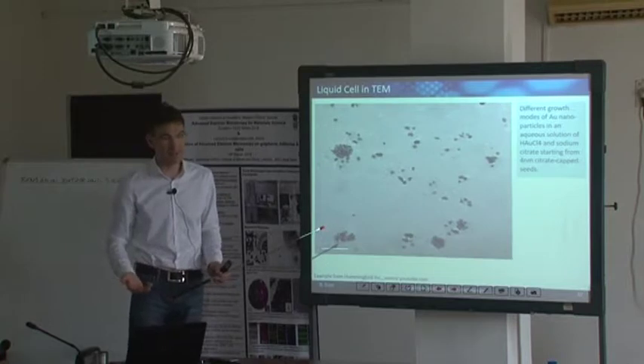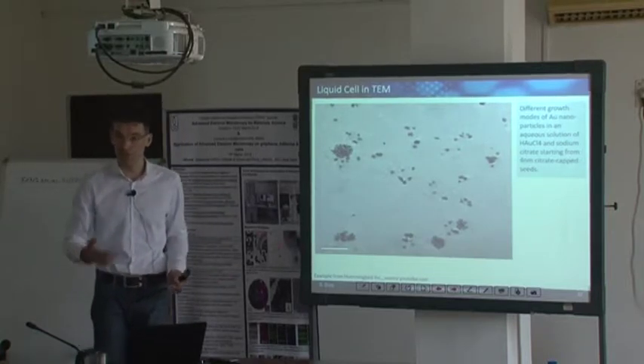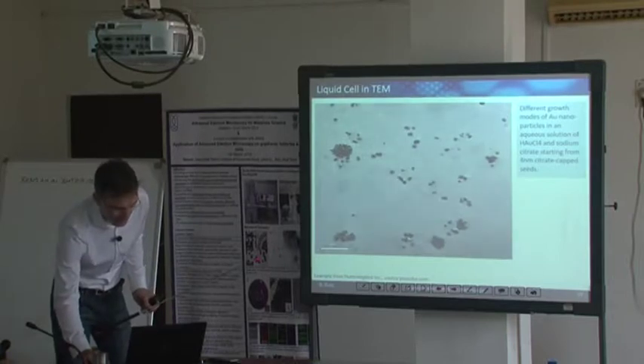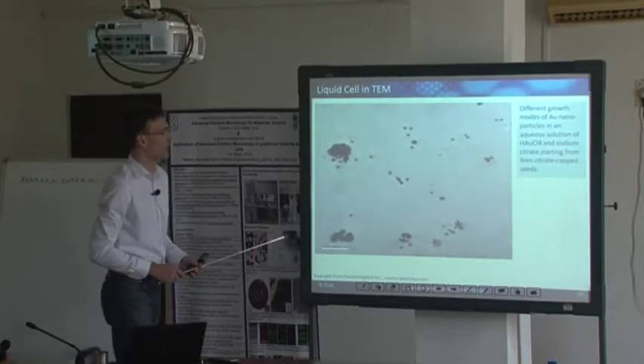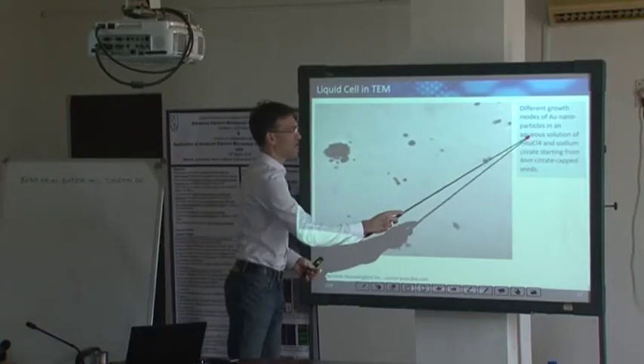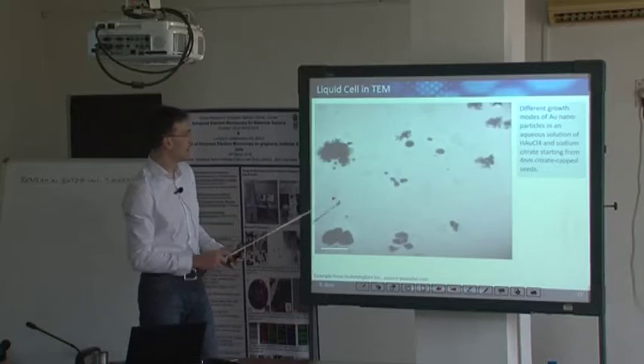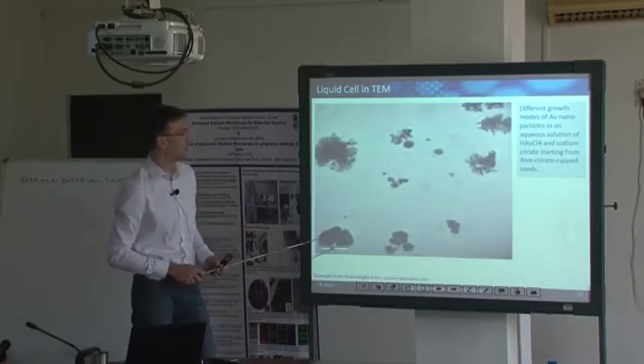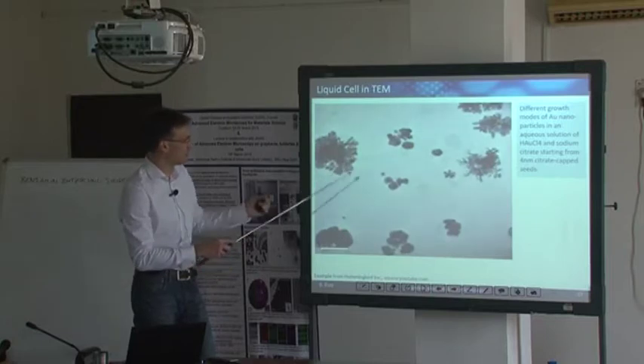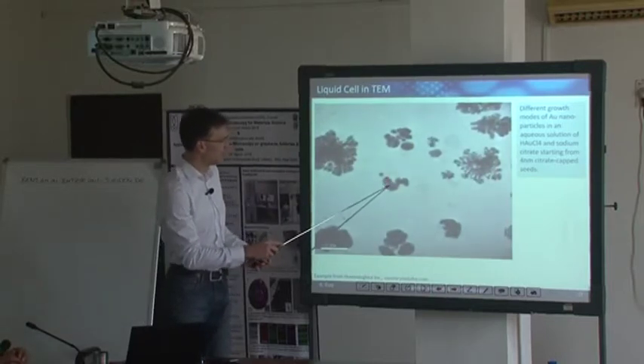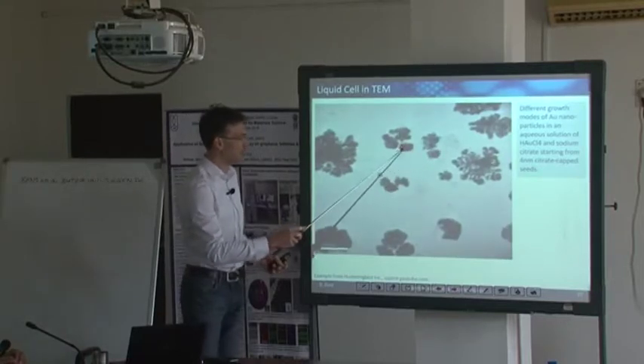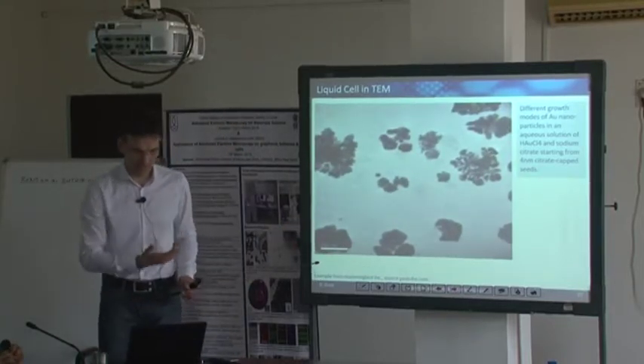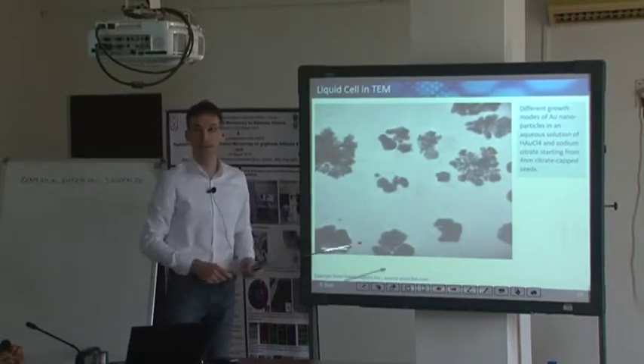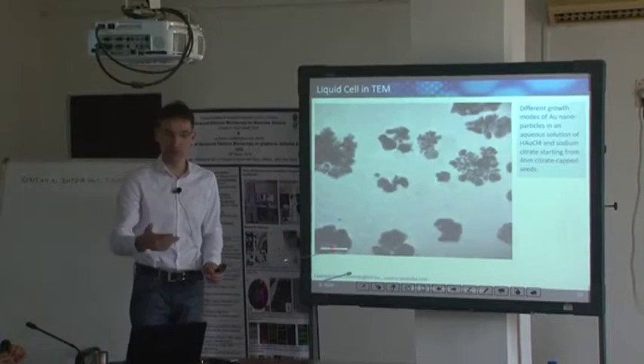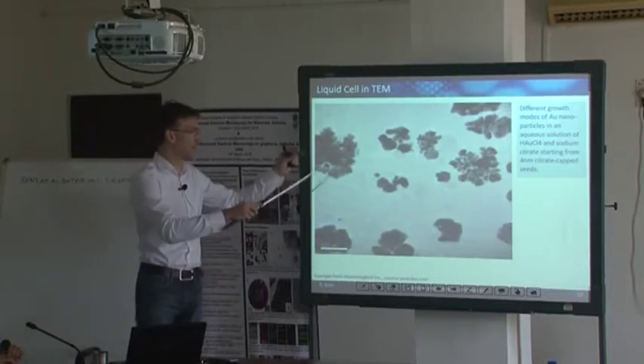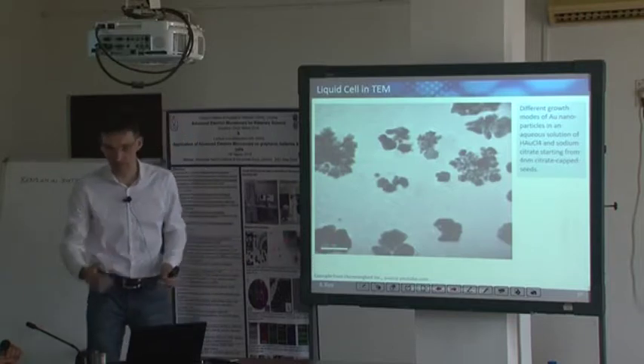Meaning if the pH is different, if you want to observe any growth of particles, that might already cause some trouble. This is the growth of gold structures, from a solution and some reaction products, and you can see that there are somehow different growth modes of these dendritic structures in this particular case, and of this continuous growth, let's say, of more homogeneous nanoparticles. And if you just see the final state deposited from a solution onto your, let's say, TEM grid, you might not understand what's going on and why those different structures form, for instance.